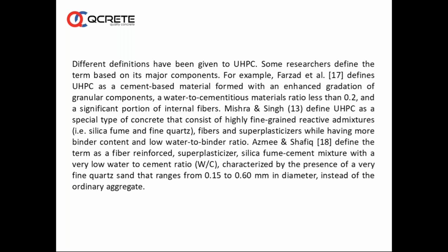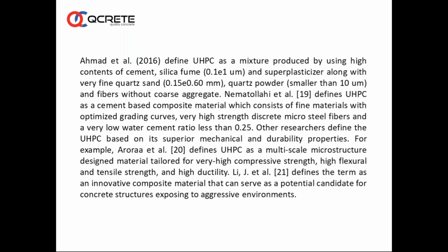as given by different people here, and we need to know that at this moment it is completely different when compared to conventional concrete, and achieving the required properties with different locally available materials will require a lot of detailed study of material characteristics, particle packing, and detailed study of all the sources of different materials and their properties. Ahmad again defines UHPC as a mixture produced by using high contents of cement, silica fume of 0.1 to 1 micrometer, and superplasticizer along with very fine quartz sand, quartz powder, and fibers without coarse aggregate.